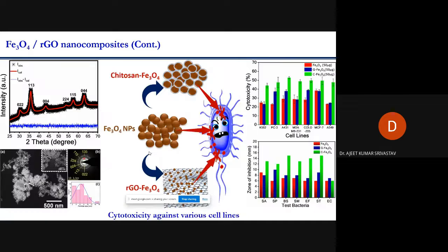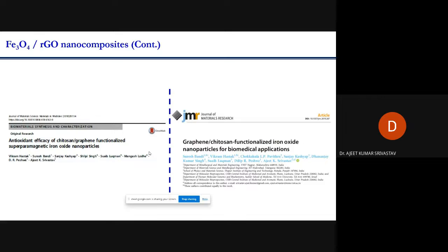Further, these nanocomposites were tested for cytotoxicity against various cell lines. Here again we showed that these functionalized nanoparticles have improved cytotoxic behavior compared to the bare one. Of these two works, one was published in the Journal of Materials Science: Materials in Medicine, the antioxidant one, and the second one, where we tested the antibacterial and cytotoxic behavior, was published in the Journal of Materials Research.